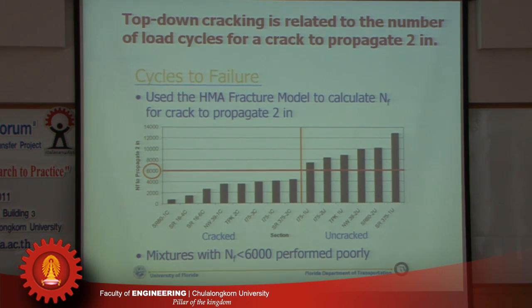What he found is that if he ran this test and it took a very high number of repetitions for the crack to propagate 2 inches, that mixture would have a very low likelihood to have top-down cracking. And that number seems to be about 6,000 repetitions. So if it takes more than 6,000 repetitions for the crack to propagate 2 inches, that mixture is resistant to top-down cracking.